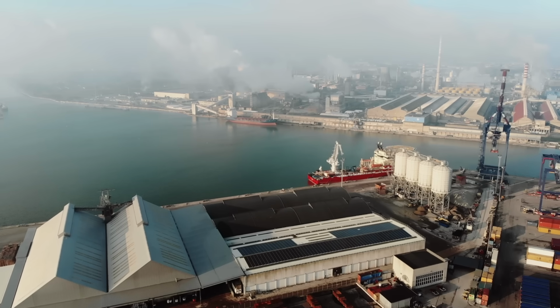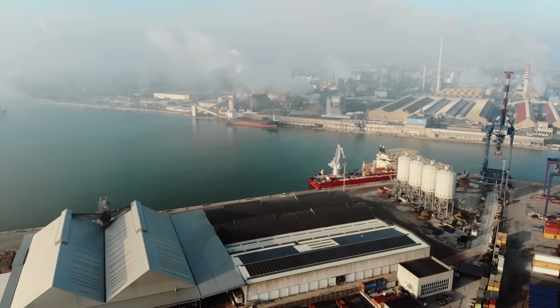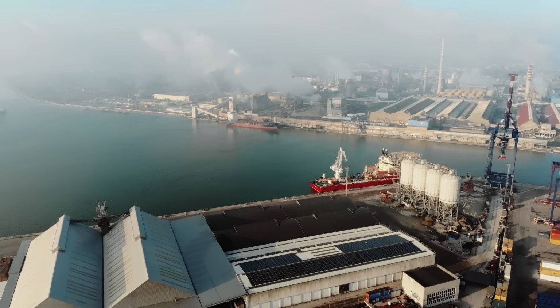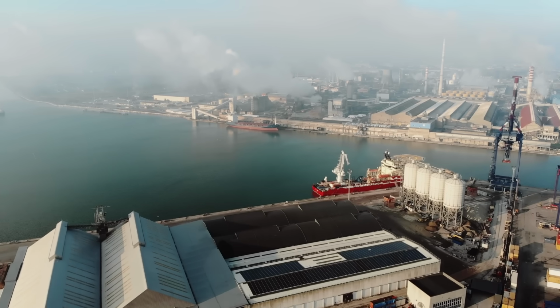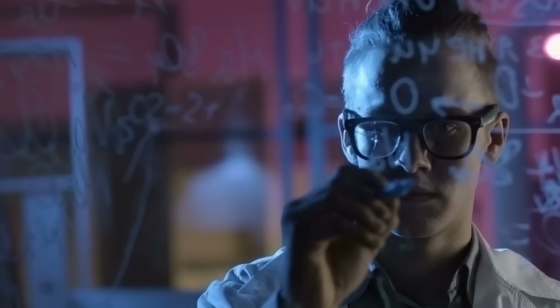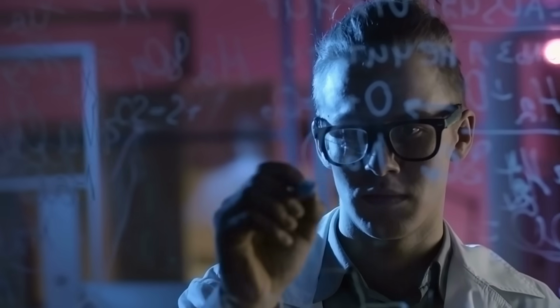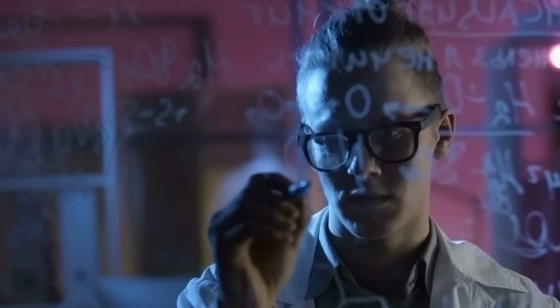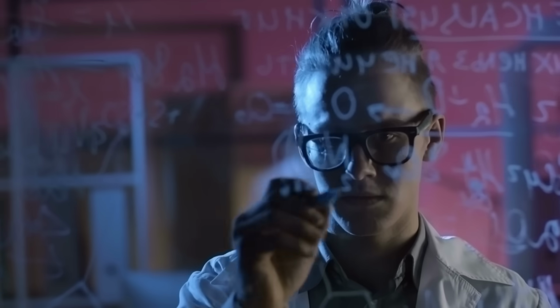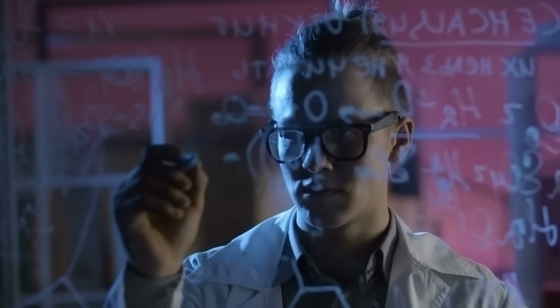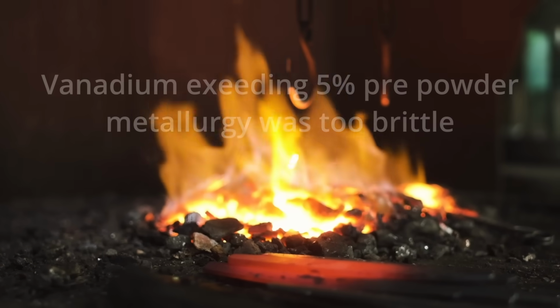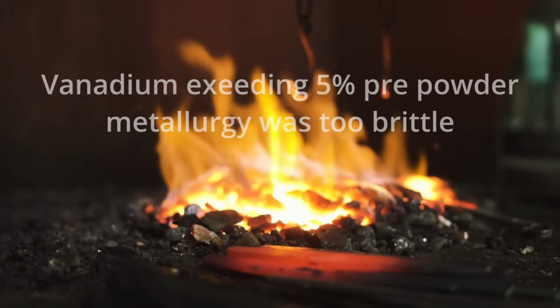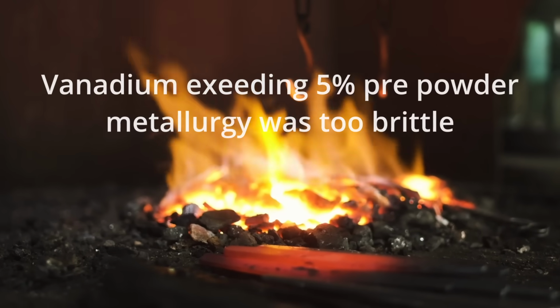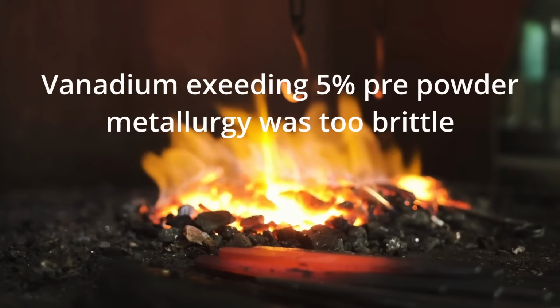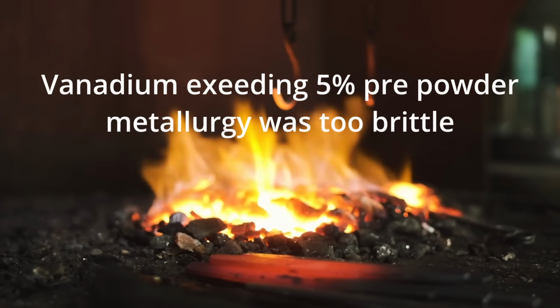To truly understand the rise and fall of CPM 15V, though, we need to go back to the beginning. Specifically, we need to go nearly a century back. In the 1930s, metallurgists determined that high wear resistance could be developed into steels by adding a higher vanadium content. The problem was that with the ingot-based process that they had at the time, any vanadium content exceeding 4 to 5% would result in a steel that lacked toughness.